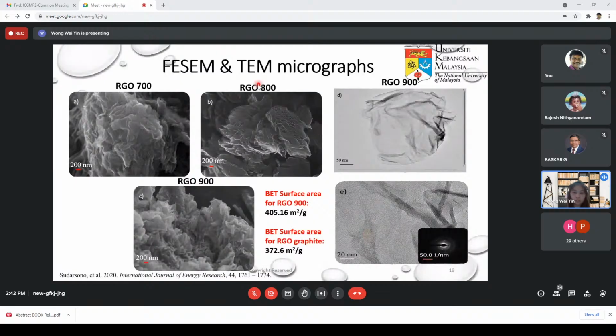This is the micrograph of the RGO produced from the biomass at different temperatures. As you can see, from 700 to 900 degrees Celsius, at 900 degrees Celsius you can see the morphology is less dense and thinner in layers. That means they have been more successfully exfoliated from the bulk structure itself. Then we look into the TEM image.